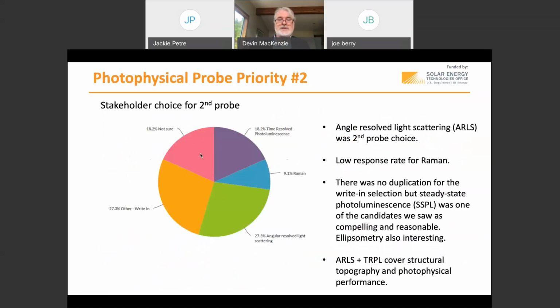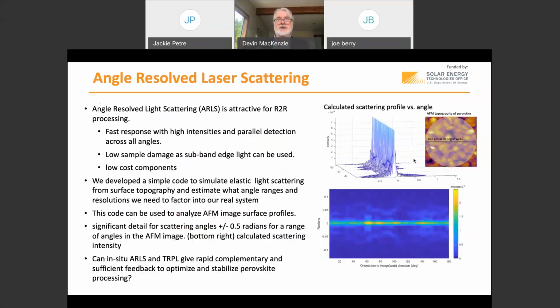We also found, as the stakeholder choice, that very few people were interested in Raman. Our first choice for the second probe to complement the TRPL was angle resolved light scattering. Angle resolved light scattering is great because it's kind of like a poor person's ellipsometry, but it can be very, very fast. It's elastic, so we can go sub-gap so that we don't have absorption and don't have to worry about photo-induced degradation. We can hit it with a big laser, put the detectors versus angle, and collect in parallel. We can get a lot of signal pretty fast. It doesn't give as much detail, but we were looking for a signal of rough grain size. Really, it's not even grain size we care about. We care about surface roughness related to the grains.